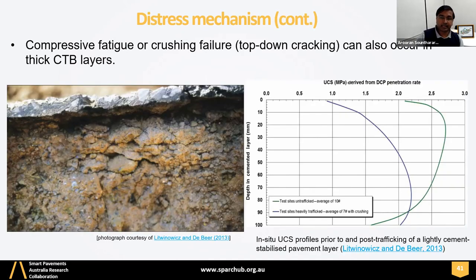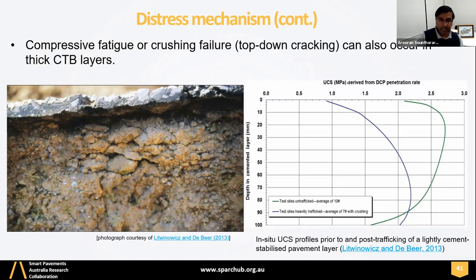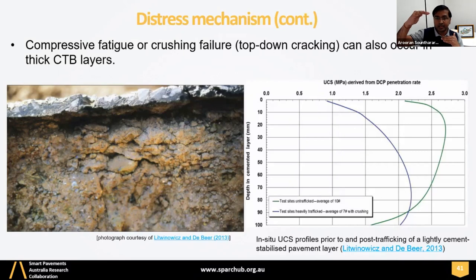Also, in pavement analysis and real pavement performance, people have identified crushing as a failure mechanism when you use a thick cementitious material. If you take a 300, 400 millimeter depth of pavement, which is commonly used in South Africa due to heavy traffic applications, your pavement undergoes crushing. So what is crushing? It is a top-down cracking in terms of fatigue, and crushing is captured in a simple way in this UCS diagram.